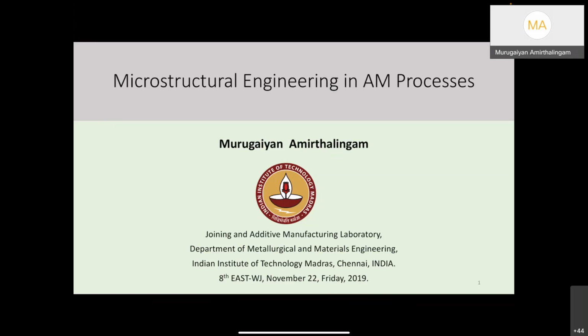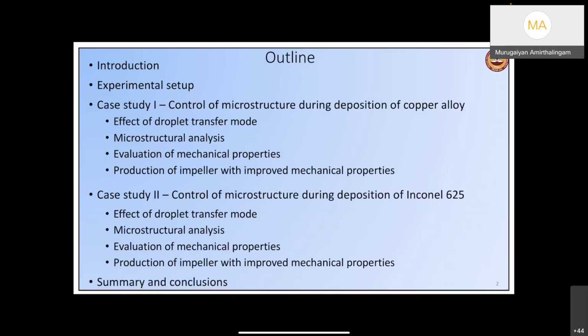Like, for example, the powder bed system, or another commonly used additive manufacturing process, the wire arc additive manufacturing process. So what I'm going to teach is 2 case studies. One is on how we can control the microstructure evolution during additive manufacturing in copper-based alloy systems. In a copper-based alloy system, when we do welding or additive manufacturing, the directional growth of grains is commonly observed, and that will lead to inhomogeneous mechanical properties based on the direction you take the sample.